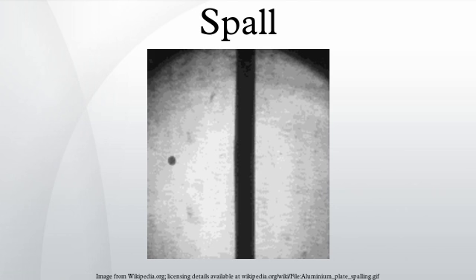Salt spalling is a specific type of weathering which occurs in porous building materials, such as brick, natural stone, tiles and concrete. Dissolved salt is carried through the material in water and crystallizes inside the material near the surface as the water evaporates. As the salt crystals expand this builds up shear stresses which break away spall from the surface. Some believe that porous building materials can be protected against salt spalling by treatment with penetrating sealants which are hydrophobic and will penetrate deeply enough to keep water with dissolved salts well away from the surface. Great care and expert advice must be consulted, however, to ensure that any coating is compatible with a substrate in terms of breathability, or other serious problems can be created. Chimneys show spalling damage before other portions of buildings because they are more exposed to the elements.